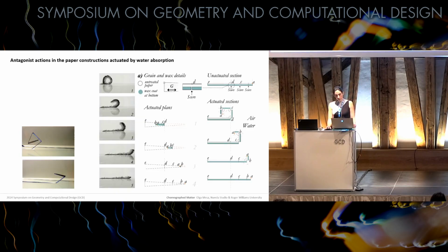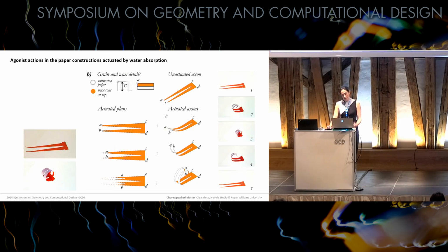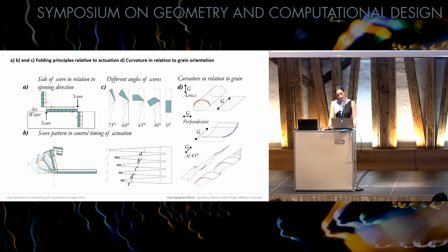So the type of movement was predicted and controlled by applying these principles and enhancing the anisotropic capacities of the paper. Here you see antagonistic actions in the paper constructions that were actuated by absorption of water at the hinges or folds and channeled to the top of the layer of the surface. These actions unfold the origami designs, whereas in the agonistic or contracting motions actuated by water absorption, the underside of the paper construction absorbs them while the top part has the wax. Additionally, the orientation of the paper grain is essential in controlling movement.